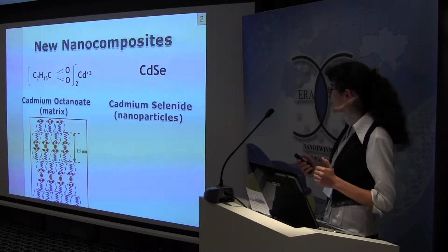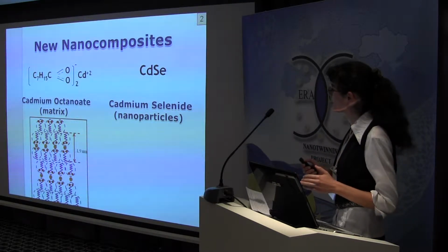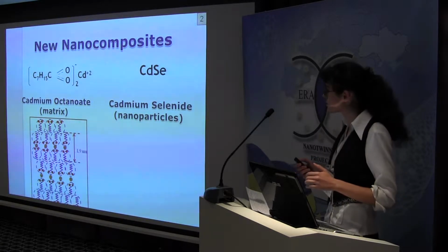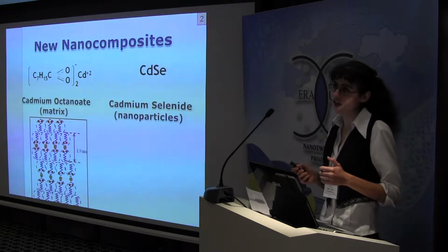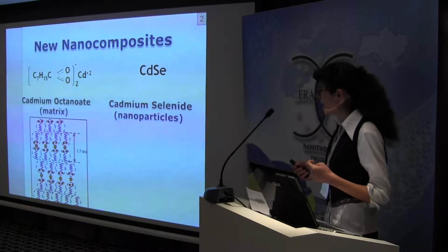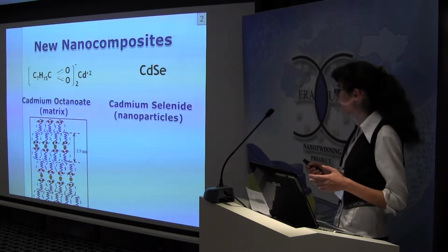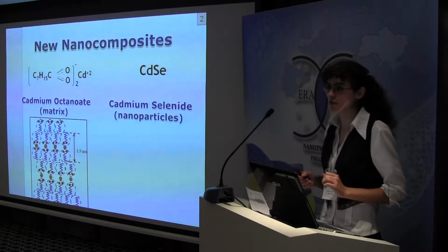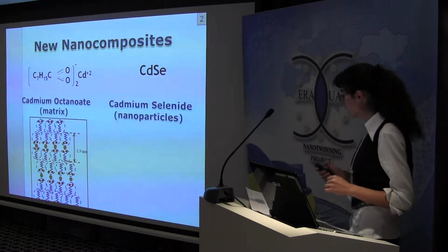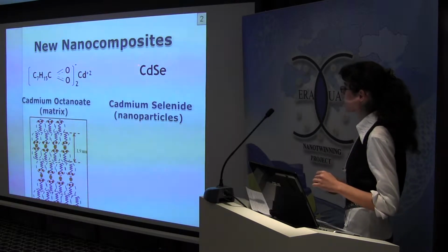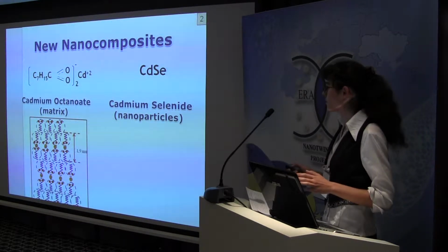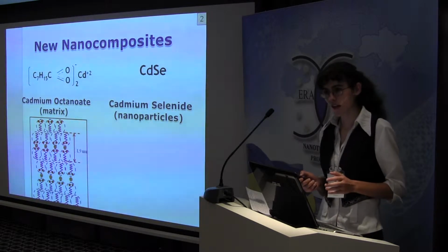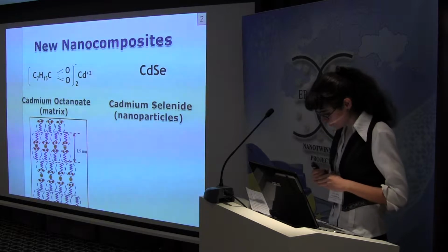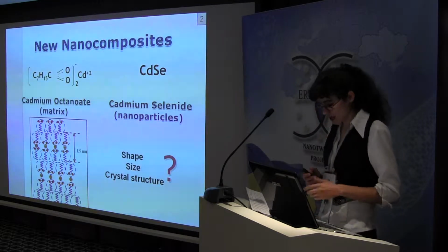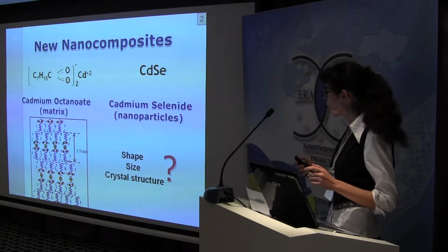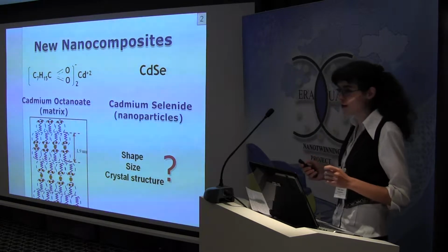We consider cadmium octanoate in two different phases. First of all, cadmium octanoate forms a thermotropic ionic liquid crystal at a temperature of 190 degrees Celsius. And it is very interesting that it keeps the liquid crystal ordering after being cooled to room temperature. Cadmium selenide nanocrystals were successfully synthesized in this matrix at the Institute of General and Inorganic Chemistry in Kiev. Primarily our goal was the investigation of shape, size, and crystal structure of these nanocrystals.